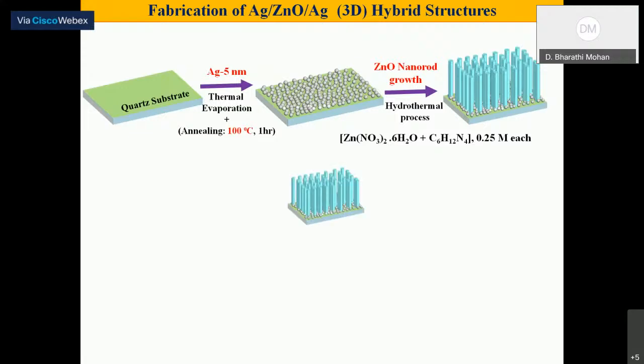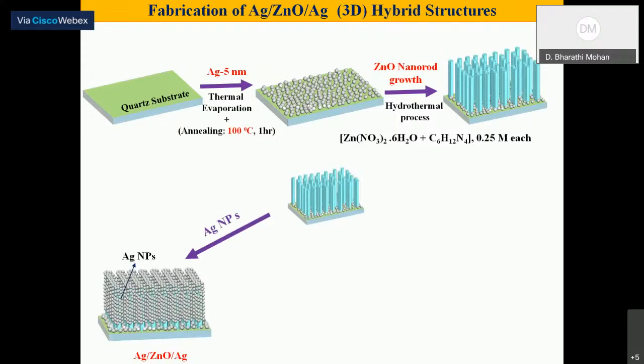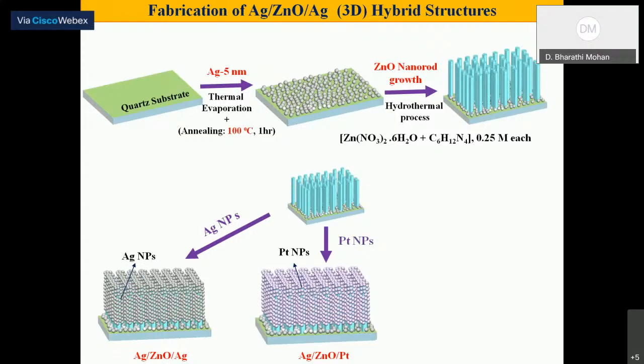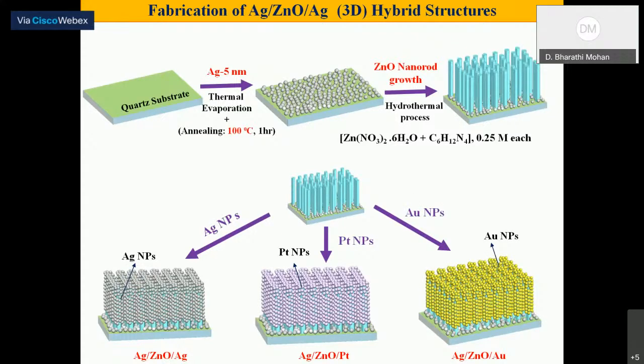And after this, we have decorated the zinc oxide nanorods with 3 different metals. One is silver, another one is platinum, another one is gold. Now you can see the silver coated substrate is called a 2D substrate, whereas silver, platinum and gold decorated on zinc oxide nanorods are called 3D substrates.